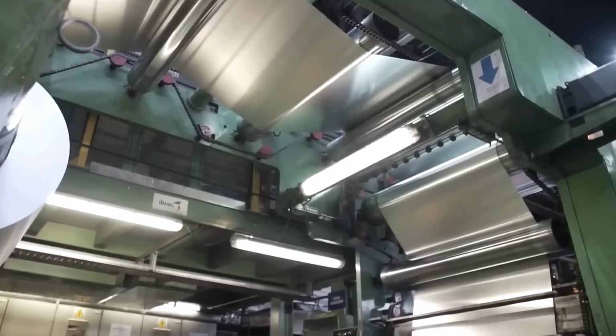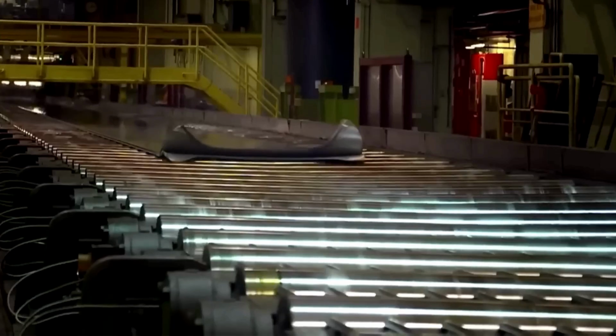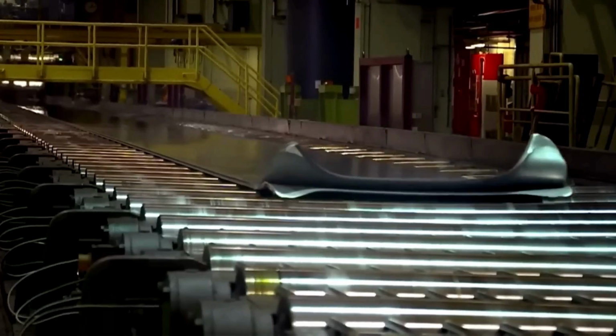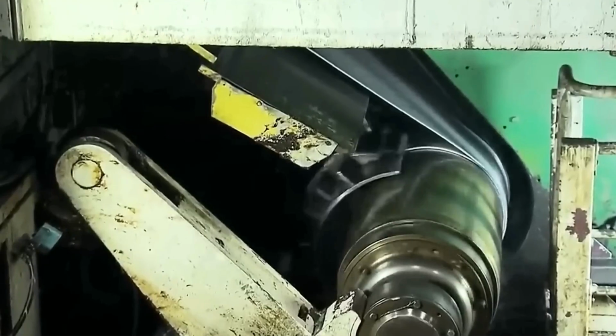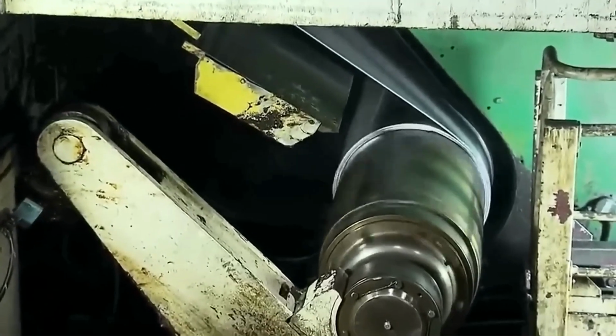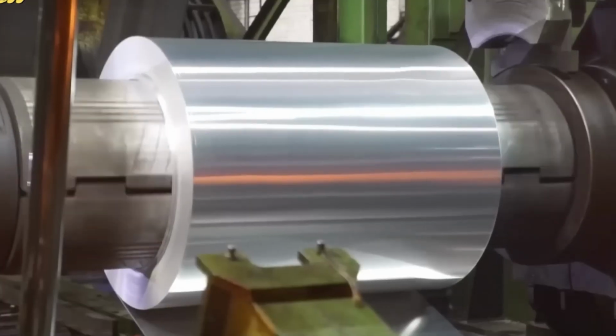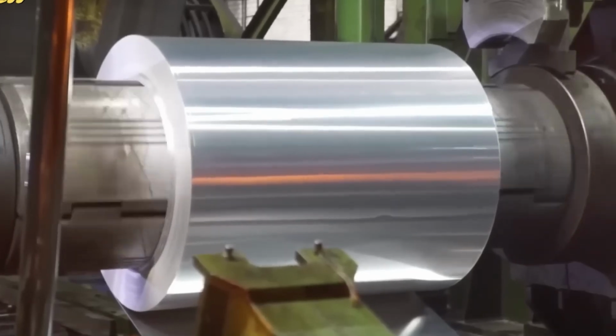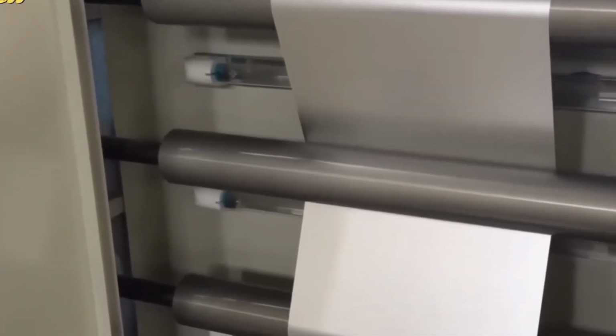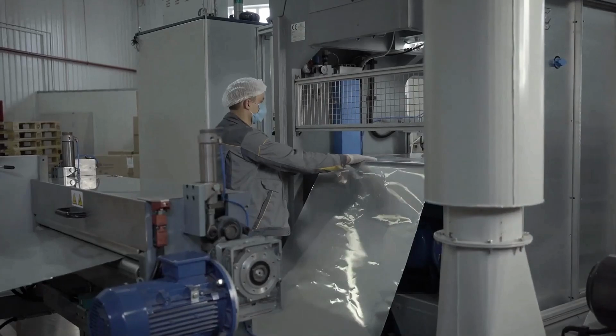Throughout the production process, the foil is subjected to rigorous quality control checks to ensure it meets strict specifications for thickness, tensile strength, and surface finish. To determine thickness, a sample is weighed and its area is measured. The thickness is then calculated by dividing the weight by the product of the area and the alloy's density.